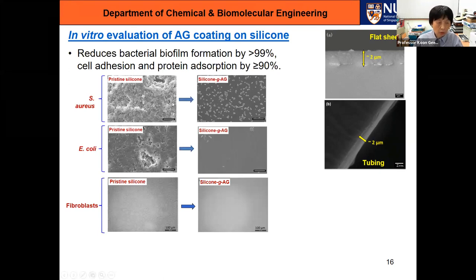This coating turns out to be quite effective in reducing bacterial biofilm formation by 99%. As you can see, this is pristine silicone. After 48 hours, it's full of biofilm. And after coating, the amount of bacteria on the surface is much reduced. It also reduces mammalian cell adhesion. This is fibroblast. And protein adsorption is also reduced by about 90%.